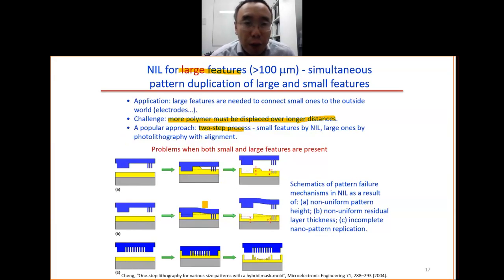Below shows you the problem with the imprint that has both small and large feature size. You can see in the first example, the mold, this large feature size got stuck. In the end, the pattern height here and the pattern height here is different. For the second case, the mold gets bended, so the residual layer thickness is not uniform. For the third case, we have the small feature size surrounded by the large feature size, so the polymer cannot flow inside. As a result, you get this non-uniform imprint.